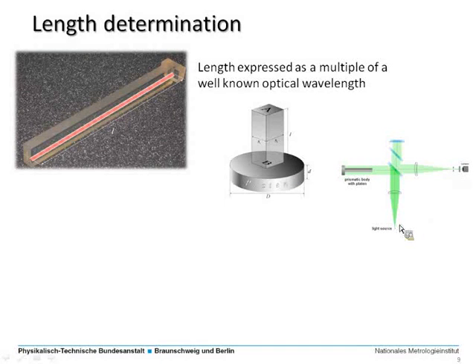Here you have a light source, most times a laser, and this laser beam is split by a beam splitter plate into two beam paths. One is the reference path and one is the object path with the sample inside. And due to this widened path, which is divergent first and then collimated, you can image the whole field of view of the whole sample surface. And by changing the length of the reference path, you can apply a certain technique, which I will explain in a minute, to determine the length of this sample, for example.